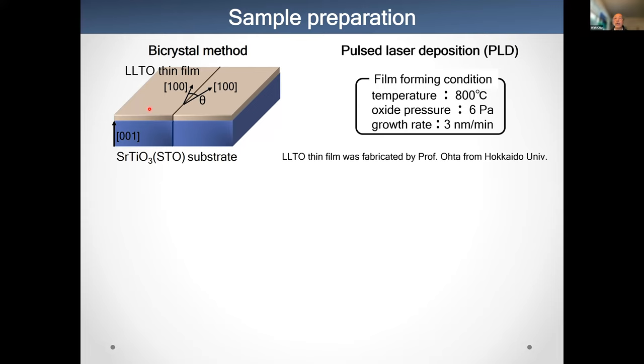Okay, good. There's a question from Lester Saluzak to Professor Ikuhara. What electron beam energy was used in the HAADF and ABF lithium imaging? And was the imaging done at room temperature or liquid nitrogen temperature? This is just room temperature. We just observe at standard room temperature. And the voltage? 200 kV. 100 kV? No, 200 kV.